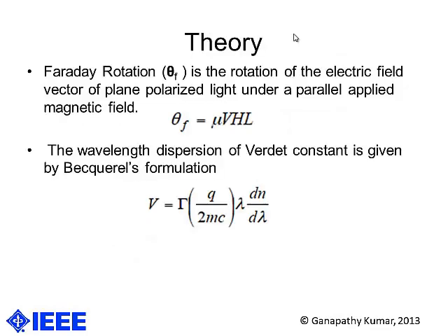So the theory that we've employed in the development of these sensors, Faraday rotation, where we study the rotation of plane polarized light under a parallelly applied magnetic field, where theta F is called the Faraday rotation angle. It's directly proportional to the magnetic permeability of the medium, the magnetic field strength applied, the length of the sample, and the V there stands for the Verdet constant, which is basically the constant of proportionality.